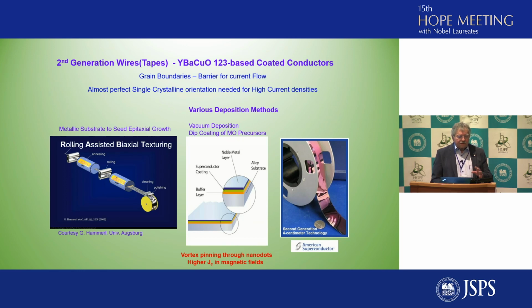So it was necessary to transform these superconductors into the form of wires or tapes. And the most advanced technology is made nowadays with the 1-2-3 yttrium barium copper oxide based coated conductors. What's needed is a support material that's mostly a metallic band. You have vacuum deposition methods which you apply to have multi-layered structures on top of these metallic substrate. And what you would like to have at the end is a flexible material, a flexible composite, in order to be able to make coils and wires.